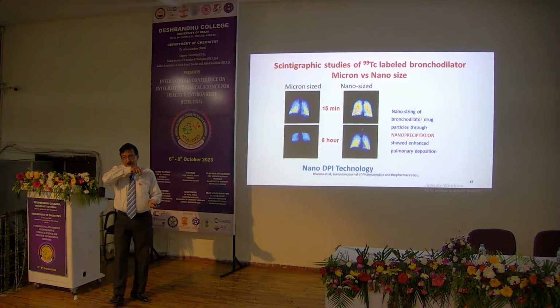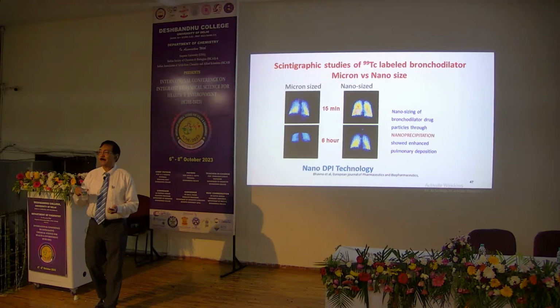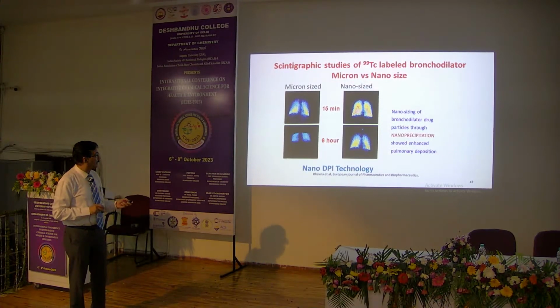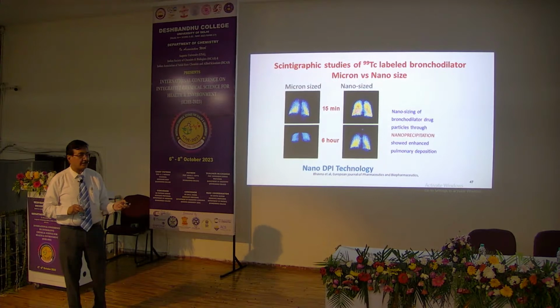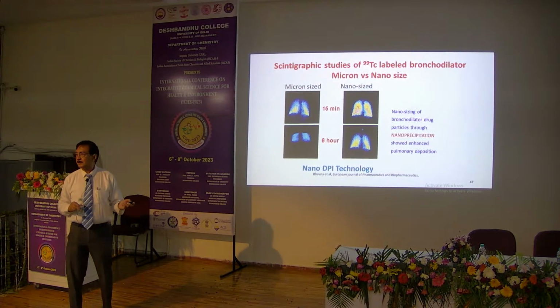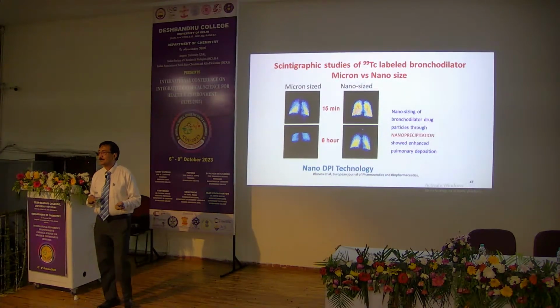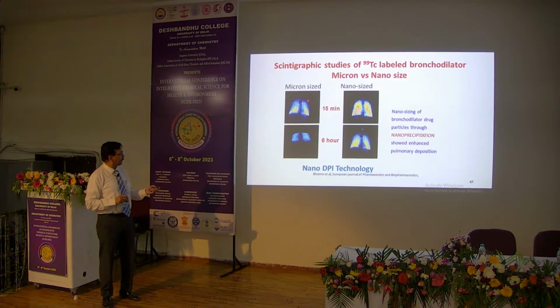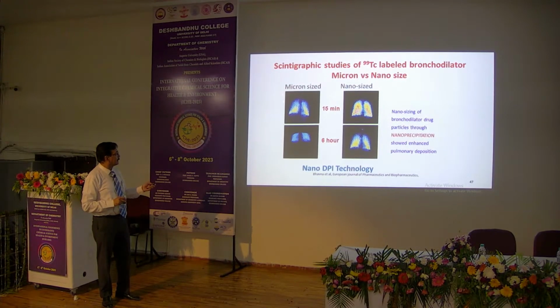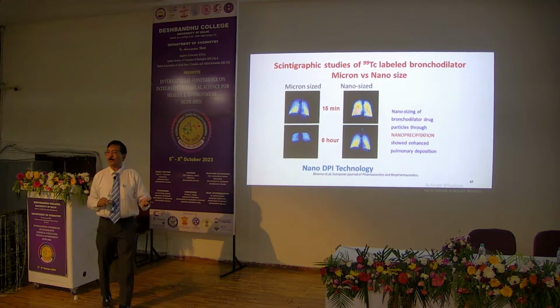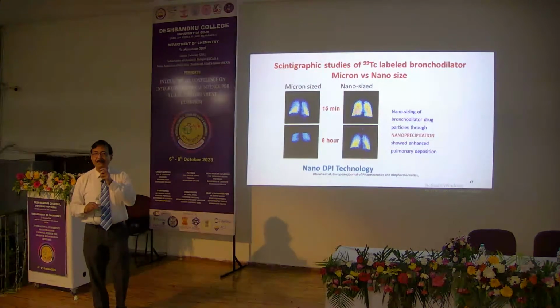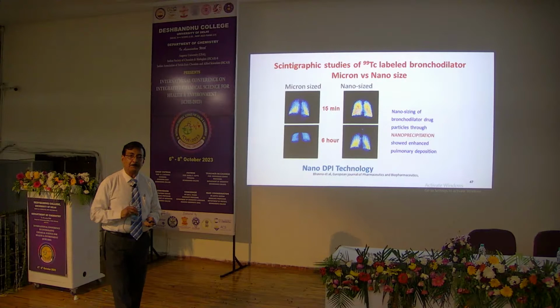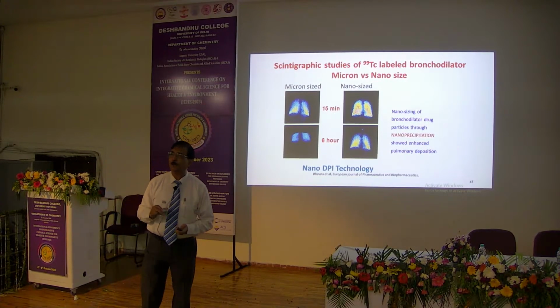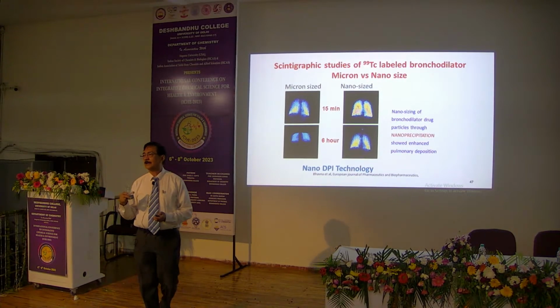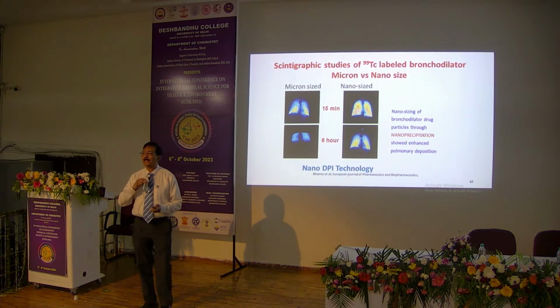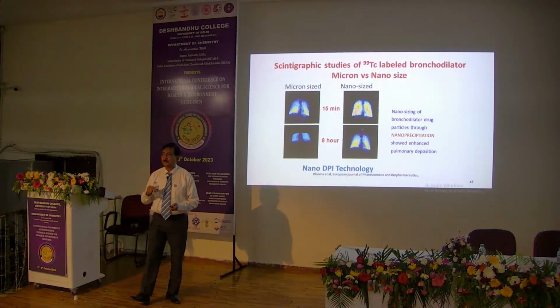And this is one product which we have developed for defense with INMAS, DRDO. We have developed respirable nano-size particles by controlling their density and particle size. In the literature, we found that for particles available in the market as dry powder inhalers, when a patient inhales those DPIs, the average lung deposition is around 30 to 40%. The rest of the drug either goes to the trachea or GIT, or it is exhaled out.